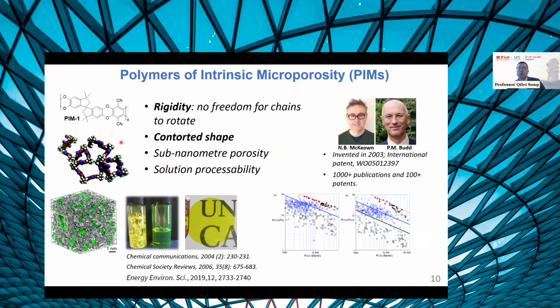So these PIM polymers are a unique class of materials because they have unique backbone structures, very different from traditional linear polymers. Traditional polymers have relatively high flexibility to move around, but these polymers are so rigid. They have relatively low freedom for the chain segments to rotate. And because of this contorted shape of the backbone, when they pack together into the solid state, they form this sub-nanometer porosity. And interestingly, these polymers are solution processable. That means you can dissolve them and cast them into membranes and films.